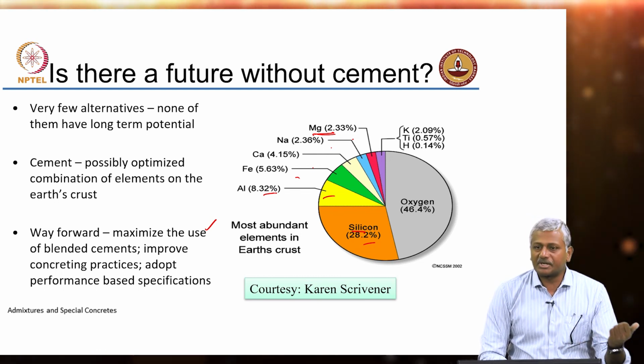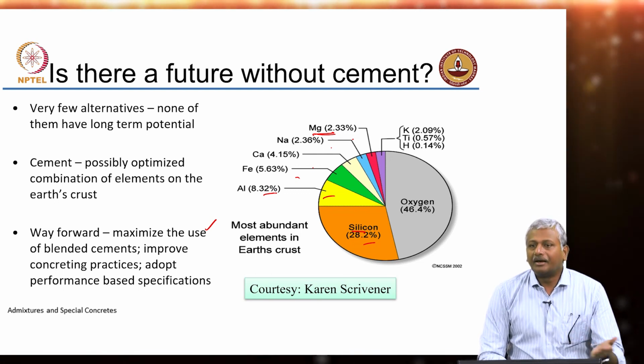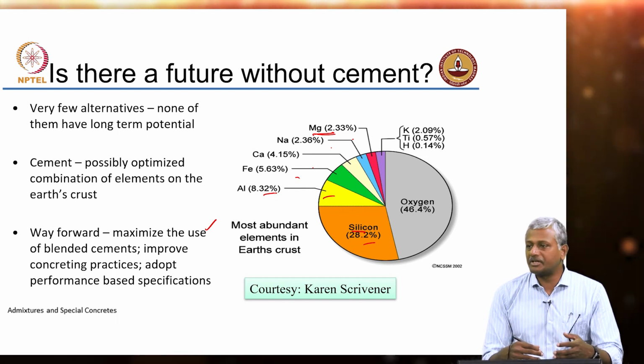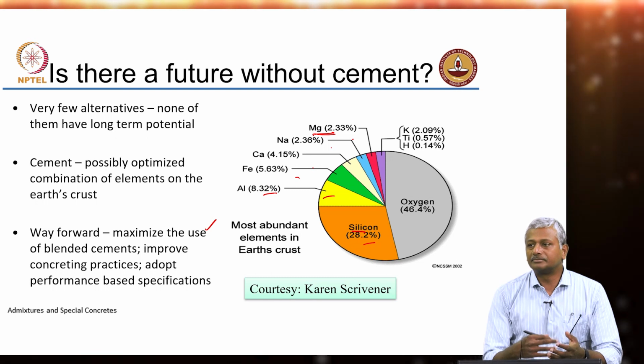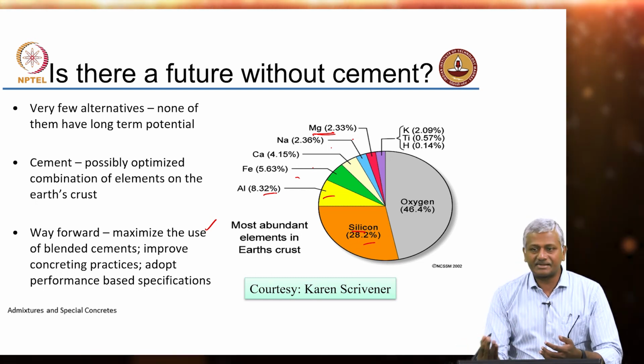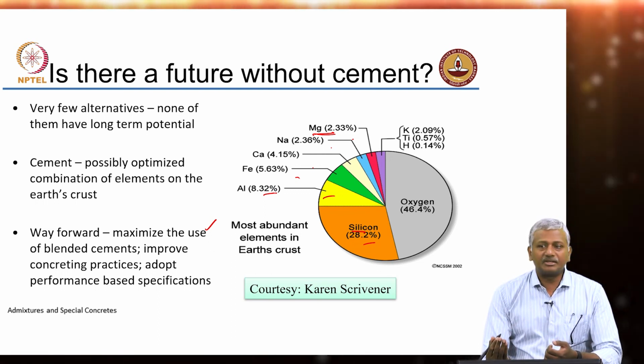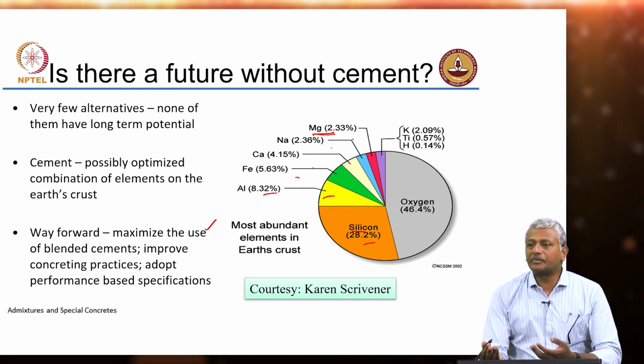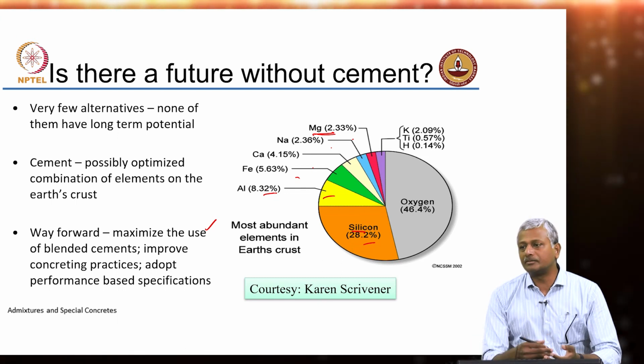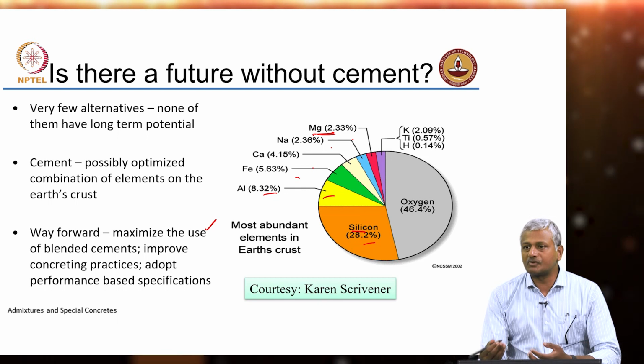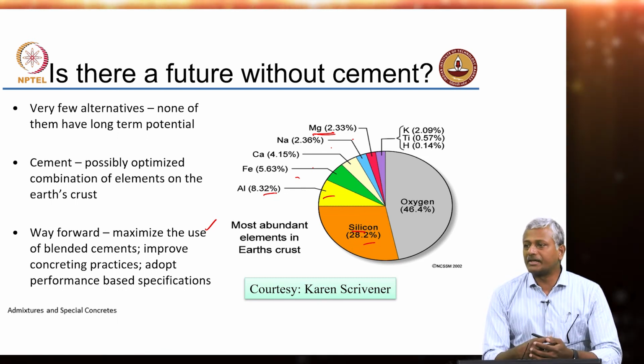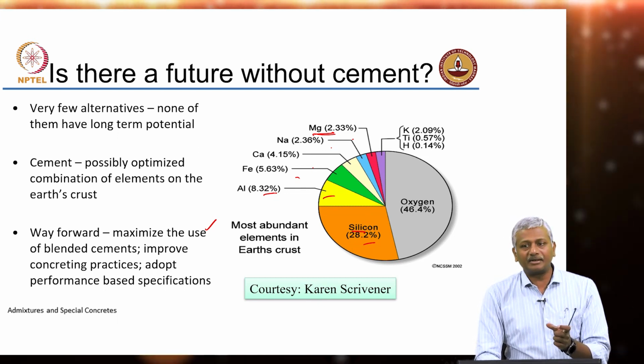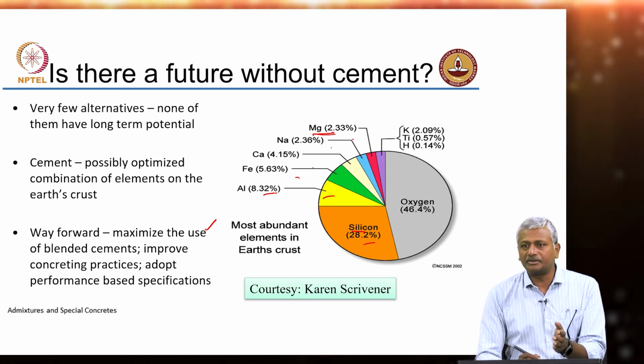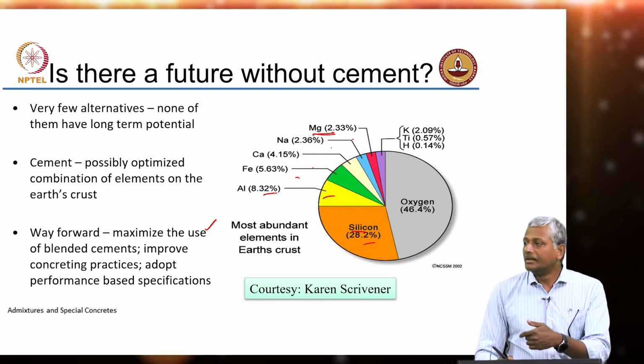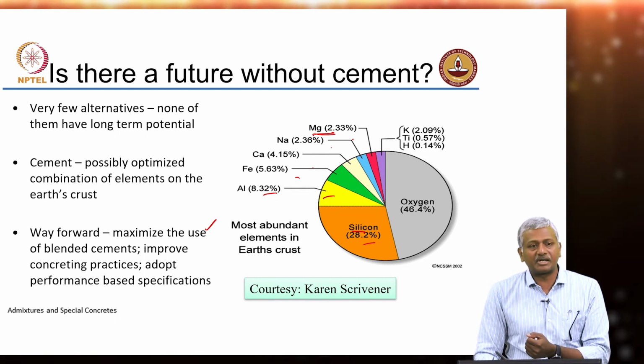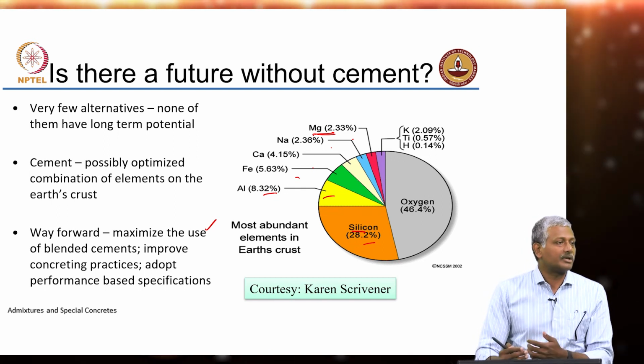Now, the same thing happens as a pozzolan also. What happens is that the aluminosilicates which are amorphous are dissolving, but then there is sufficient calcium available from the cementitious system to combine with the aluminosilicates to form calcium aluminosilicate hydrate, CASH gel, right. Now, instead of cement, if you have an alkaline solution which has a lot of sodium or potassium, what is going to happen is instead of calcium aluminosilicate hydrate, you will form sodium or potassium aluminosilicate hydrate, right. The activator solutions will basically combine with the dissolved aluminosilicates to form that. The only difference being that calcium aluminosilicate hydrate is a small polymer, short polymer. There are not too many monomers in the chain of CSH, whereas when we talk about geopolymeric systems like NASH, sodium aluminosilicate hydrate, that is like a 3-dimensional network, okay.